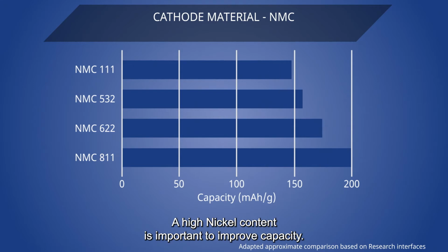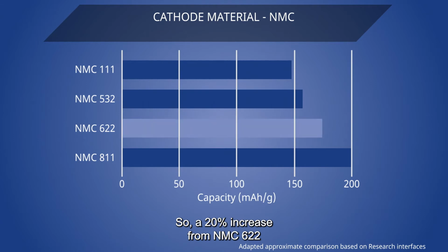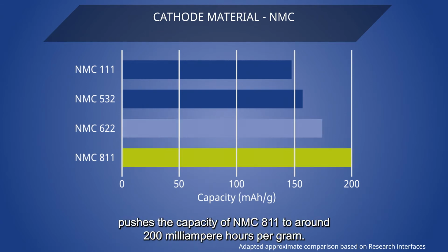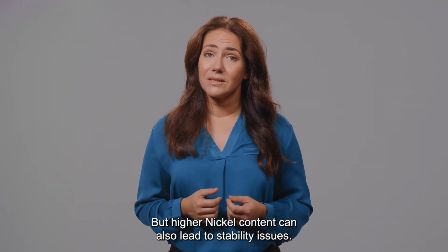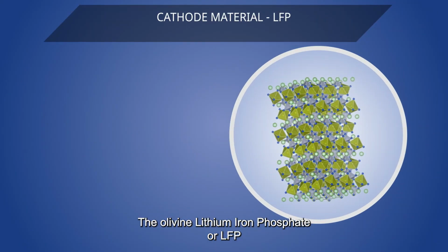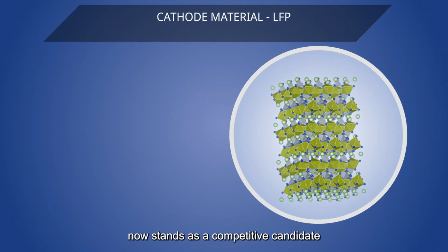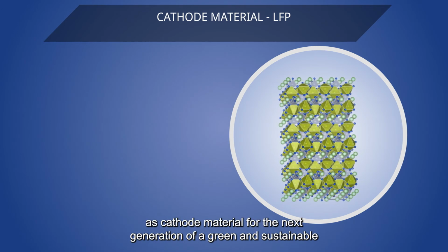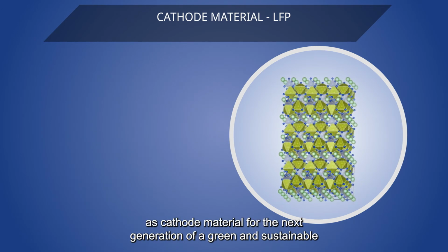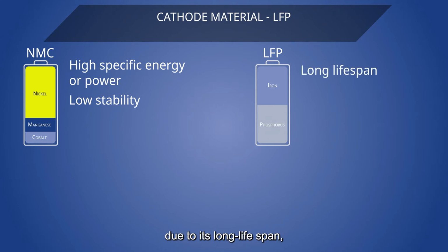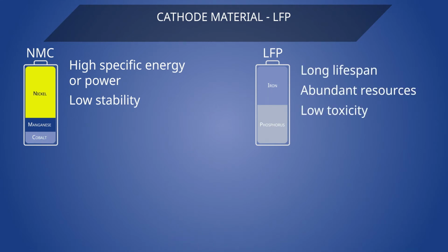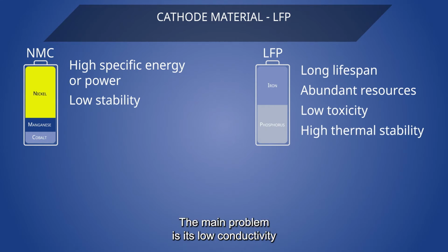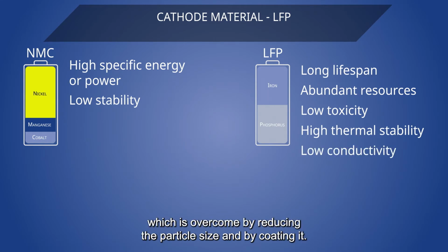A high nickel content is important to improve capacity, so a 20% increase from NMC 622 pushes the capacity of NMC 811 to around 200 mAh per gram. But higher nickel content can also lead to stability issues. The olivine lithium iron phosphate, or LFP, now stands as a competitive candidate as cathode material for the next generation of a green and sustainable lithium-ion battery system due to its long lifespan, abundant resources, low toxicity, and high thermal stability. The main problem is its low conductivity, which is overcome by reducing the particle size and by coating it.